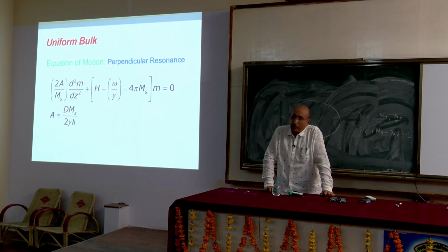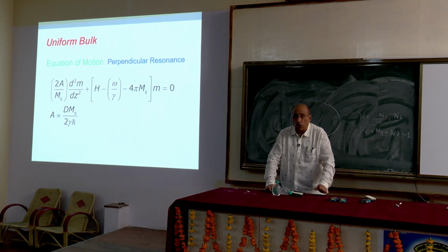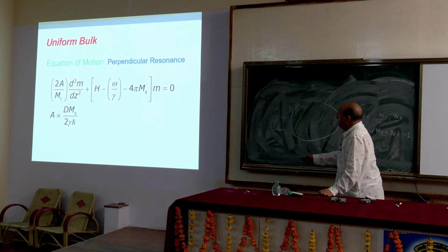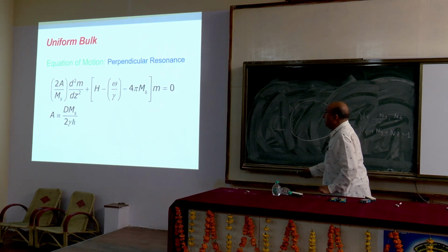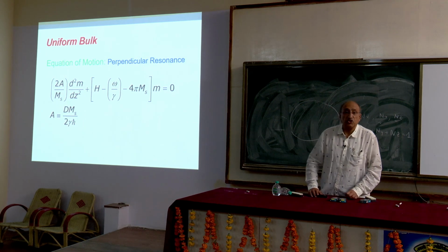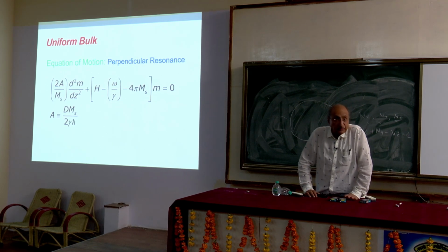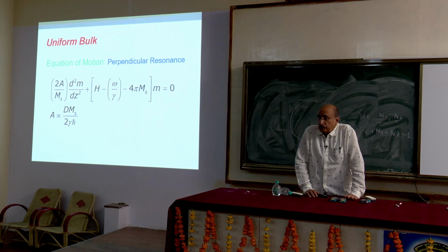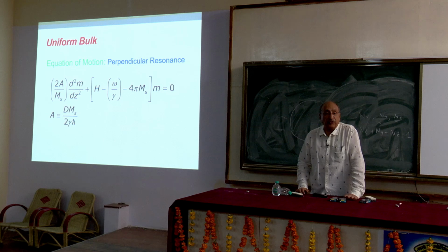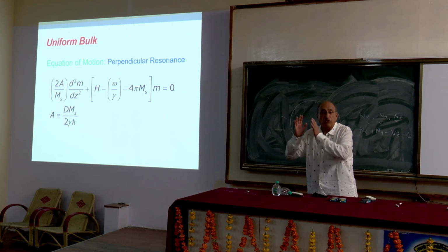This we have discussed in terms of domain walls. If you have to create a domain wall, you have to work against exchange, because exchange is trying to bring them together. Hence, in this equation there is an exchange constant A appearing, which is related to the exchange stiffness constant by this expression. So exchange has also started appearing if you are getting a non-uniform precession for any reason. But this equation is valid when everything, like magnetization, anisotropy, etc., is uniform across the film, but because of some boundary condition or something else, you are seeing a non-uniform precession in the system.